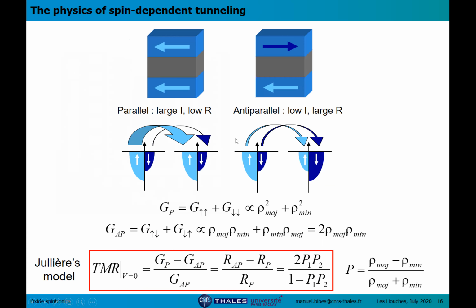This can be understood quite simply in the frame of spin-dependent tunneling, again assuming that you have two channels in parallel, one channel of current carried by spin up and another channel carried by spin down, and you assume as well that you have no spin flips. The spin memory is conserved in the process. Suppose that you work with this kind of system, you have this spin-dependent density of states. You see that for the spin-up channel here, you have a lot of states available at the Fermi level in the first and the second electrodes. So this will lead to a large tunneling current and a small tunneling current for the spin down. But because the current is flowing in parallel, you will end up with a large current and a low tunnel resistance.